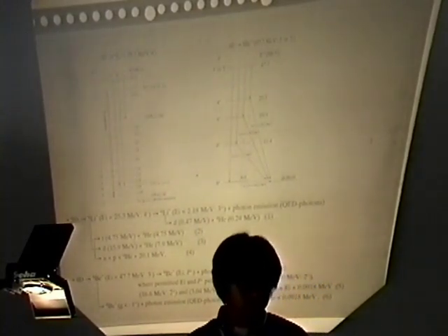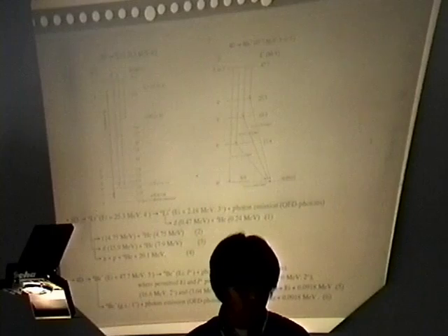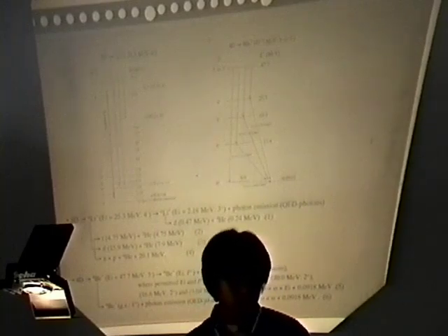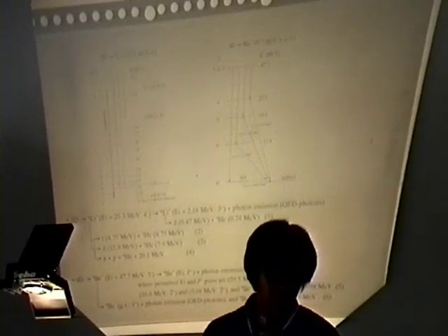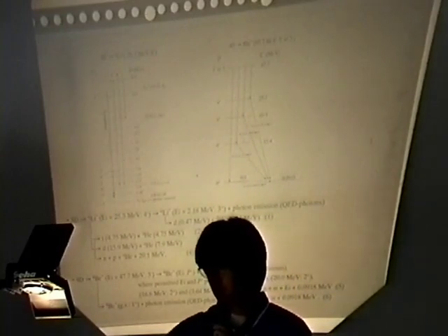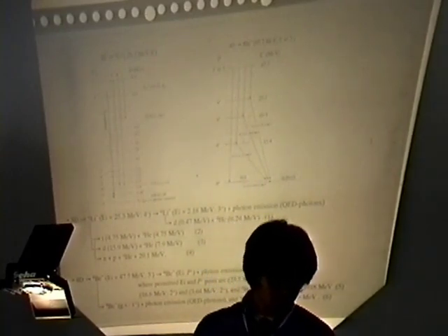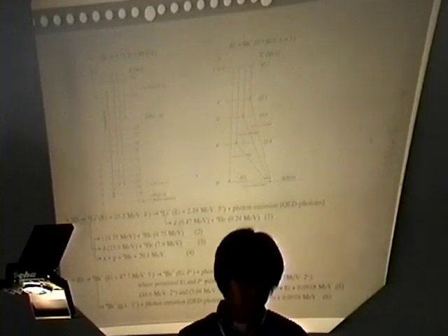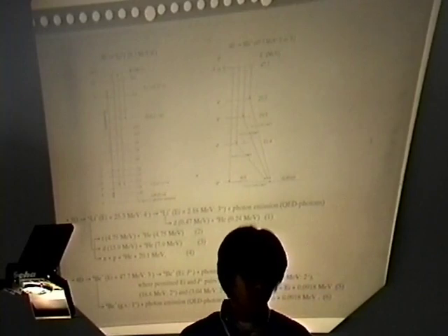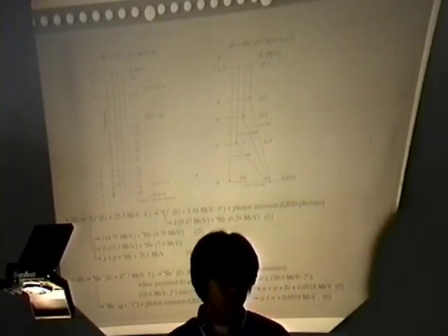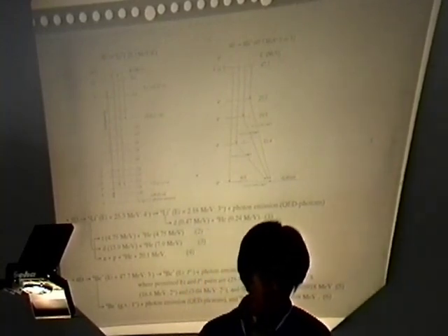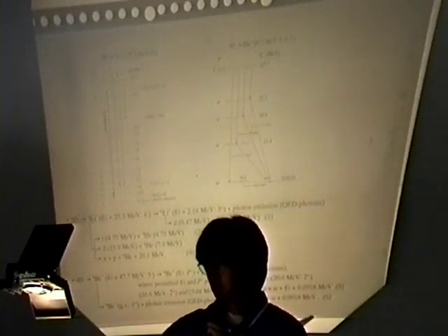Results of the electrolysis experiment, such as helium-4 generation without neutron emission, can be explained by reaction 1, 5, or 6. There is a possibility that the signals detected in the electron beam irradiation were Bremsstrahlung X-rays from the slowing down of those charged particles by 1 or 6.